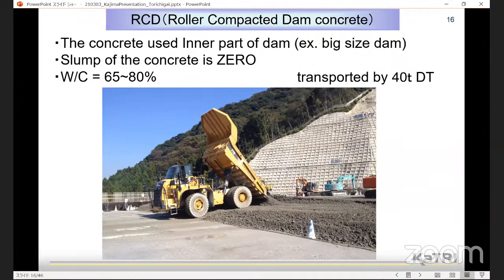This slide shows the RCD, roller compacted dam concrete. RCD concrete is one of the concretes used for the inner part of the dam. It is applied to big size dams. RCD is very hard. The slump of the RCD concrete is 0. Therefore, it is transported to the site by a dump truck, as shown in this photo. The water cement ratio of the RCD concrete is ordinarily 65% to 80%, like this.